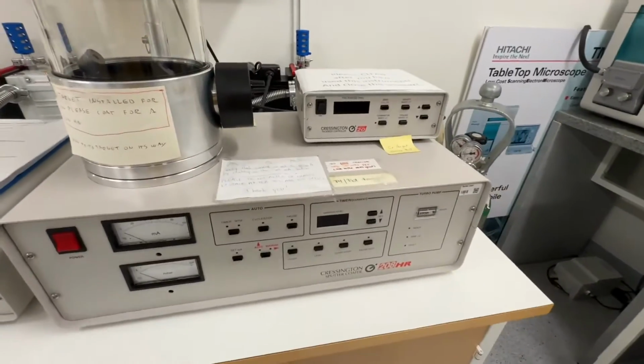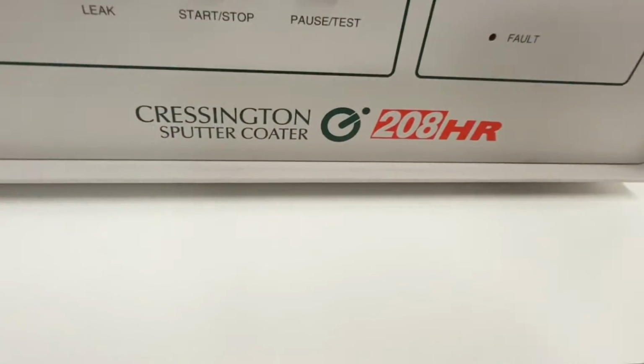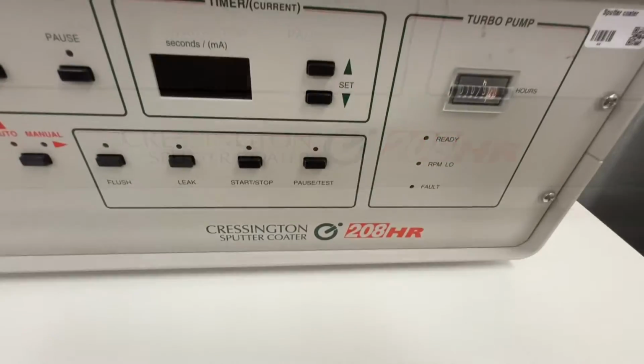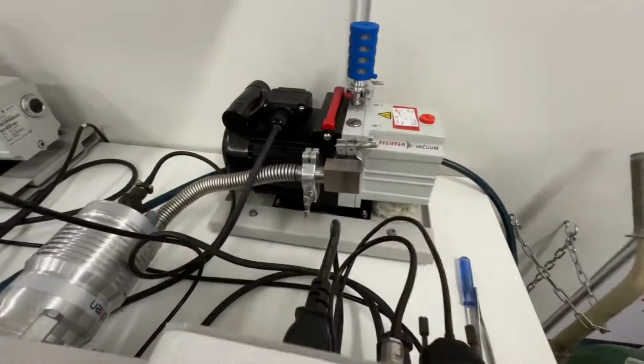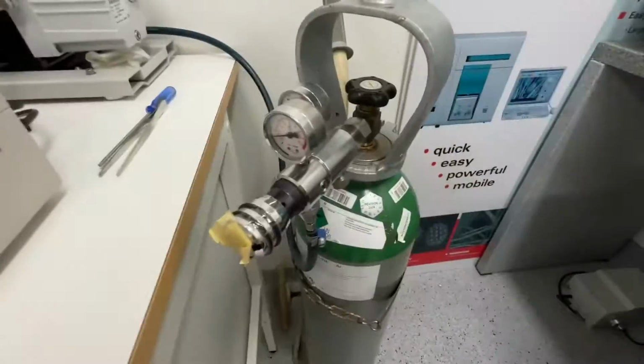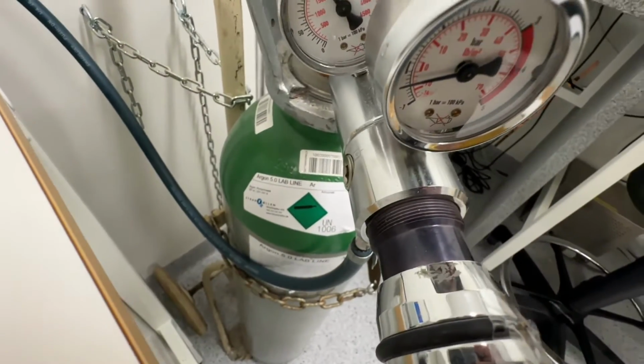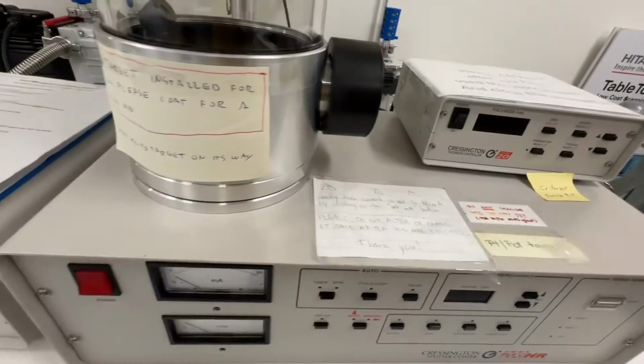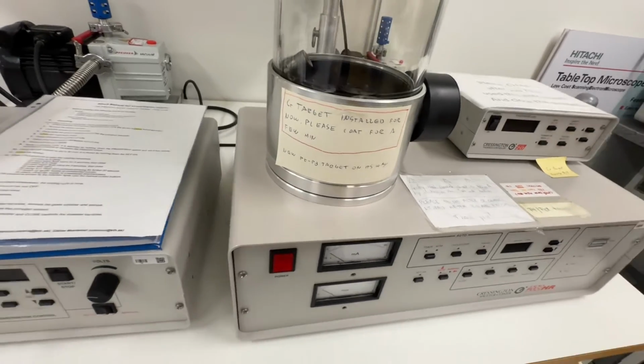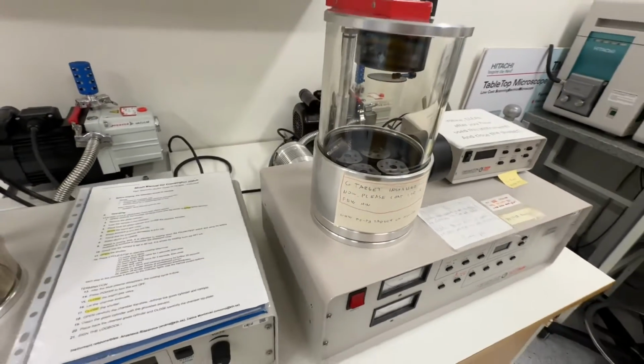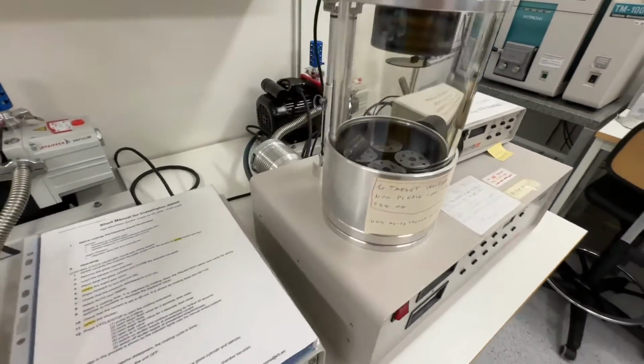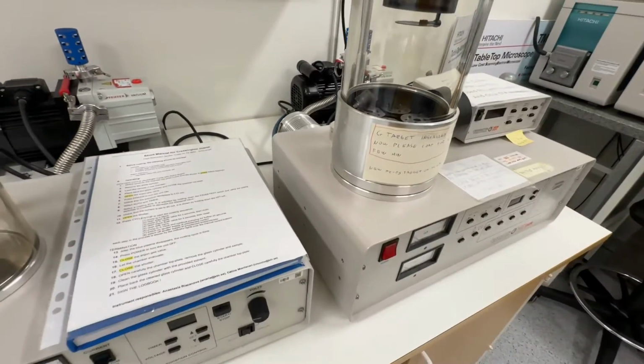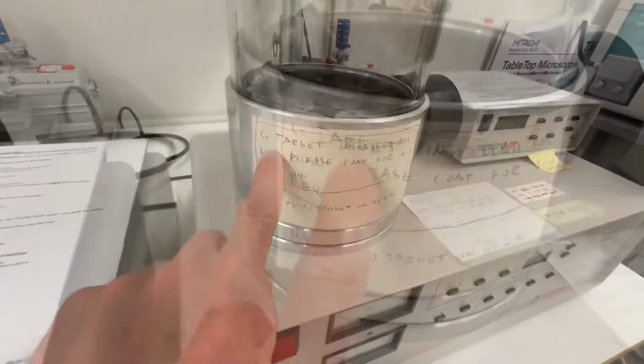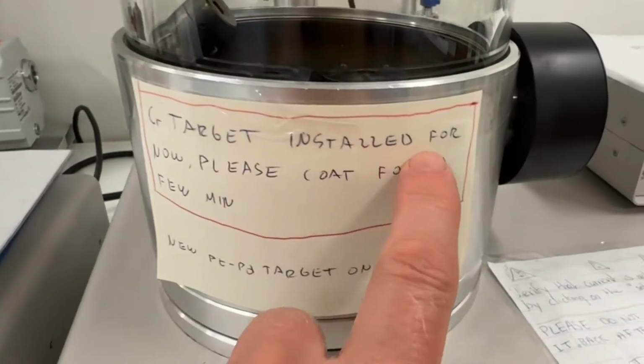So in front of me here I have the Cressington Sputter Coater 208HR. It's connected via turbo vacuum pump to our argon supply. Essentially all these things are operational. The only issue we have is that we've been running short on the platinum palladium target for a while, so we've been using a chrome target. And as you can see here, chrome target installed for now.